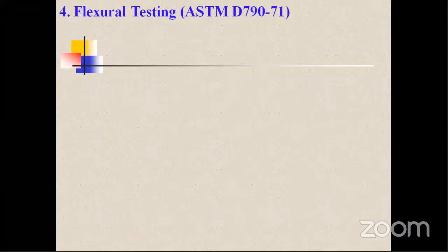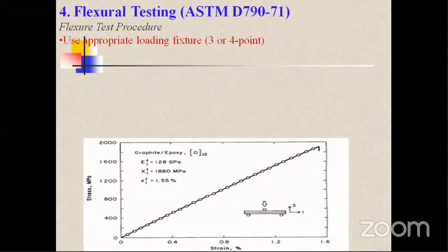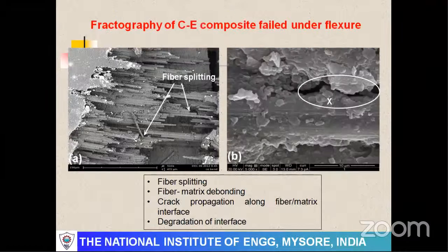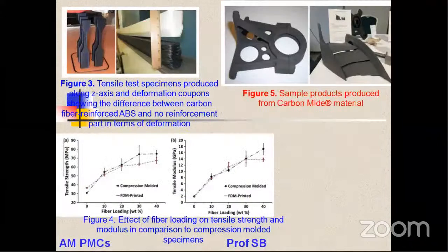Then coming to flexural testing, that is the 3-point bend test, and also the short beam test for evaluation of interlaminar shear strength. You can go through ASTM D790. After fracture, using SEM you can study how the fiber failures or particulate failures occur, whether there is debonding, any voids, all those mechanisms, or the surface topography of the failed samples, which you can also examine using a scanning electron microscope.